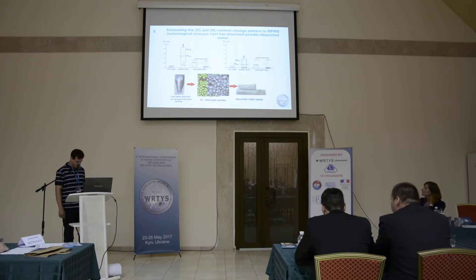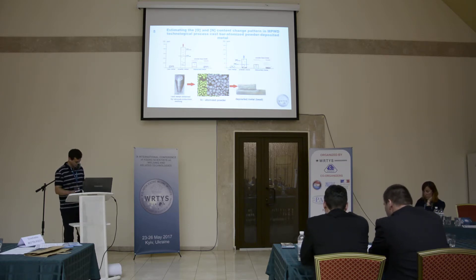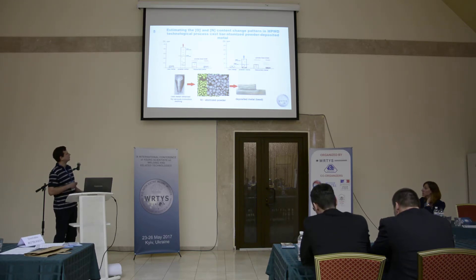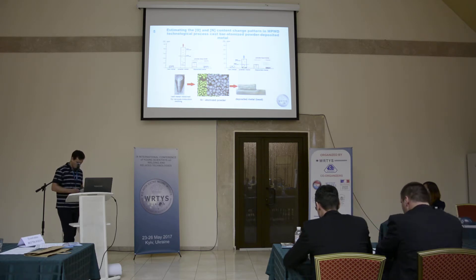The microplasma powder deposition process can be presented as a set of the following nickel-based superalloy technological conversions: firstly, cast metal obtained by vacuum induction melting; then atomized powder; and thirdly, deposited metal. The first two technological conversions engender some heritage in the form of impurity oxygen and nitrogen content at the stages of cast metal and powder metal, with certain removal of oxygen and nitrogen during deposited metal crystallization, which converts to an oxide layer on the bead surface.